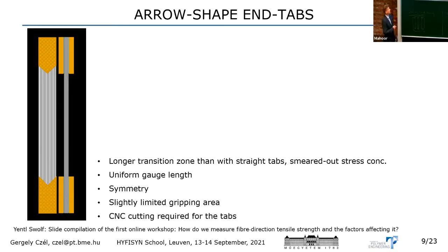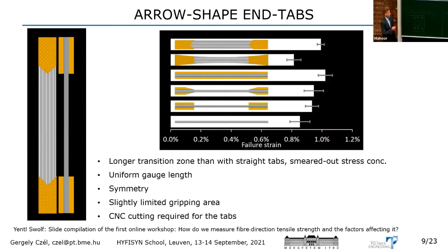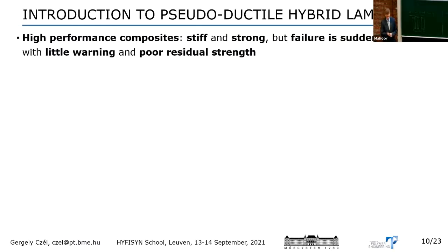But again, manufacturing, fabrication of the specimens is slightly more difficult than the standard one. So we need a CNC cutter, usually water jet cutting, to make our end tabs. On the other hand, quite promising results are being generated with this approach. It has not been published yet. So I'm referring to Yentl Swolfs' slides here. But it seems that significantly higher failure strains can be achieved with these arrow-shaped end tabs than with standard specimens.